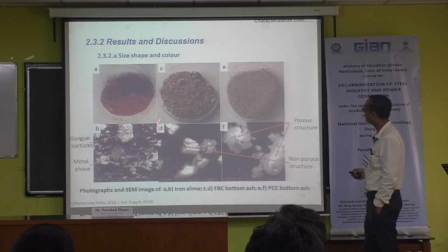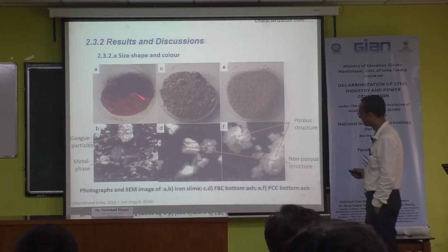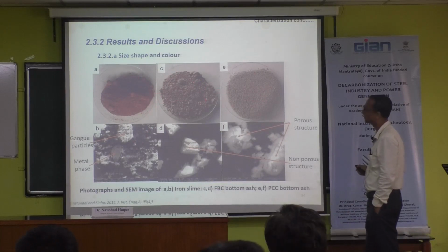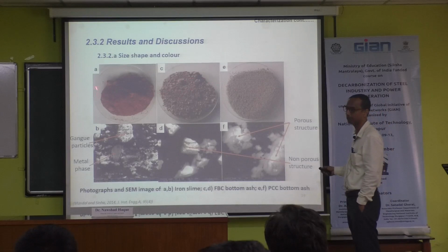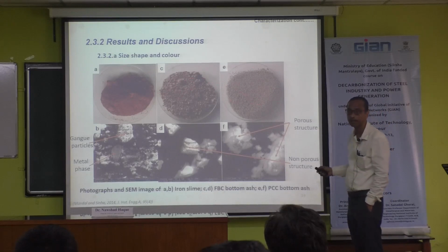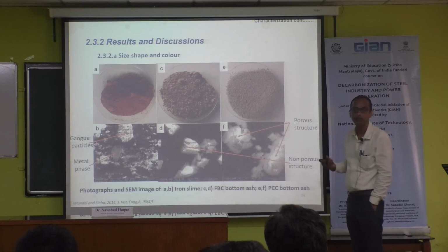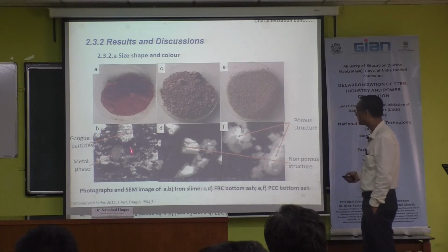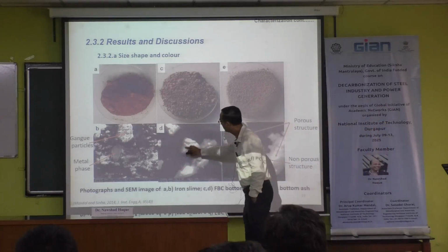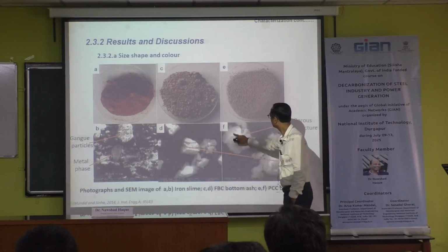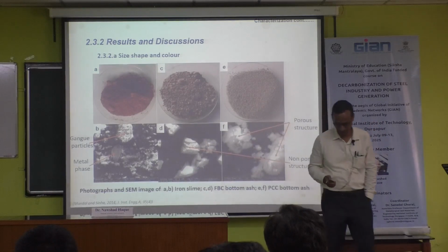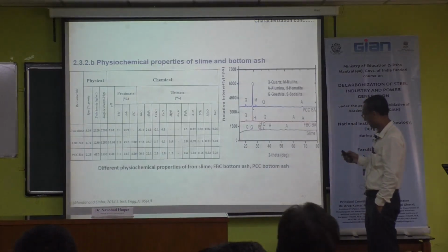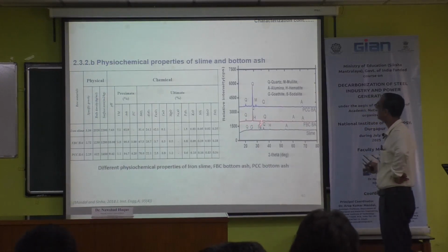Then this is the result. If you see these three materials, iron ore slime, the FBC bottom ash and PCC bottom ash, you can see the distribution, right? You can see the compact structure, and it is very fine. But here you can see agglomerated ones, porous. From the image, you can see these are solid particles, but here you can see hollow particles, a compound structure and porous structure. Then you see almost similar composition in this, this is XRD analysis.